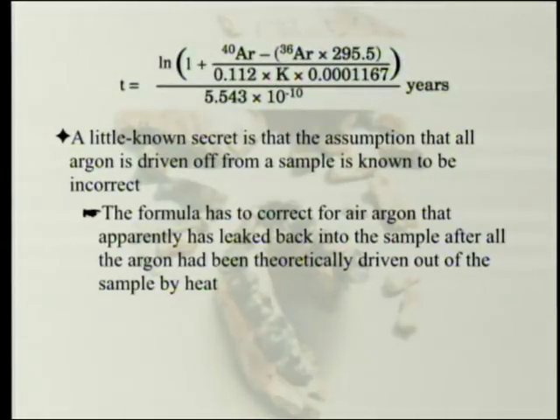That's right. You see this section right here, 36 argon times 295.5. That is the ratio of 40 to 36 in air. And so they have to subtract out the argon that diffused back in, supposedly. It's there all the time. Did it diffuse back in, or did it just never get driven off?